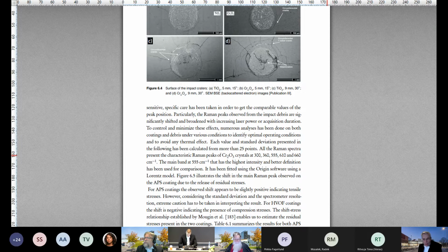Yes. So you do an erosion of the surface or wear of the surface, and then you monitor the particles. That would be the zero residual stress reference, and then the coating would be compared. So I think it's an excellent tool, but you didn't have time to add that into your publication, I guess. No, in fact, it was a micro impact fatigue test that was used for this, and it was expertise of the team in Belfort. So I had returned to Finland and I received the results later after publication, but I was able to add them to this, luckily.